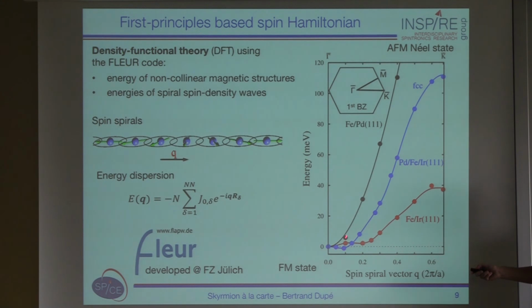Instead of having a fast rise of the dispersion curve close to the gamma point, you actually have a very flat dispersion curve close to the gamma point. And this energy here is actually very small. So in that case, you have a very frustrated system, and you need to consider magnetic interaction beyond the second order, namely biquadratic and four-spin interaction, to explain the ground state of the system.